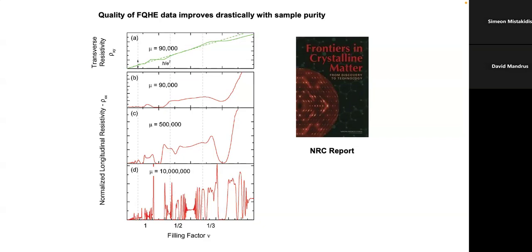This plot is from this report from the NRC called Frontiers in Crystalline Matter. This mu here is something called mobility. It's basically a measure of how fast the electrons can be accelerated, or how much they can be accelerated. The purer the sample, the higher the mobility. And you can see that with very high mobility samples, all of these features are predictable from first principles theory. So all these features are real and predictable.